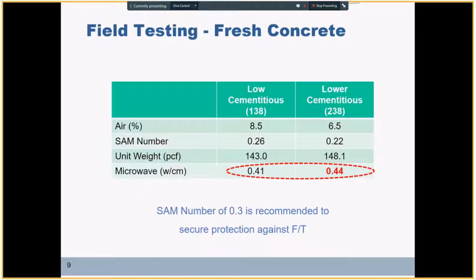Going through the data, both mixtures had good air void system. The SAM number was less than 0.3 for both of the mixtures, with 6.5% and 8.5% air in fresh state. But the actual water to cementitious material ratio in concrete made with 470 pounds, the lower cementitious mixture, was a bit higher than the design value. The microwave test results are showing a 0.44 actual water cement ratio for this mixture, which we later on will see affects the drying shrinkage behavior of the concrete used in this cell.